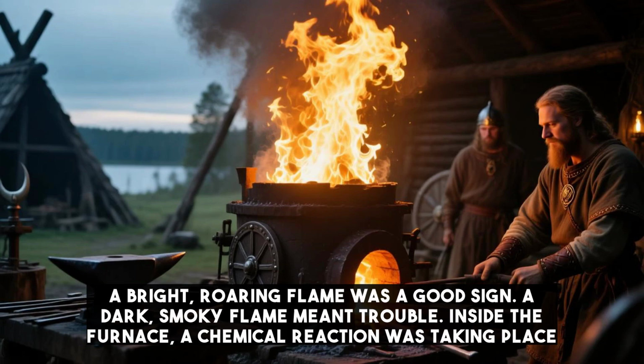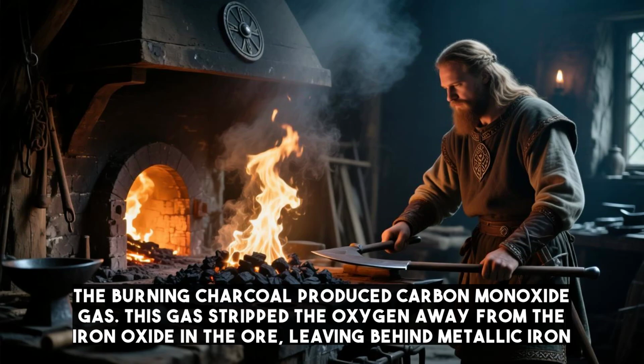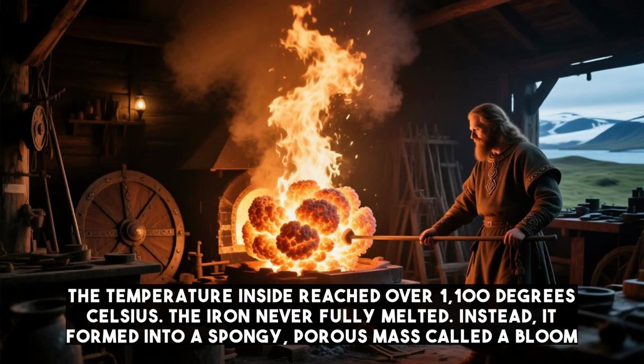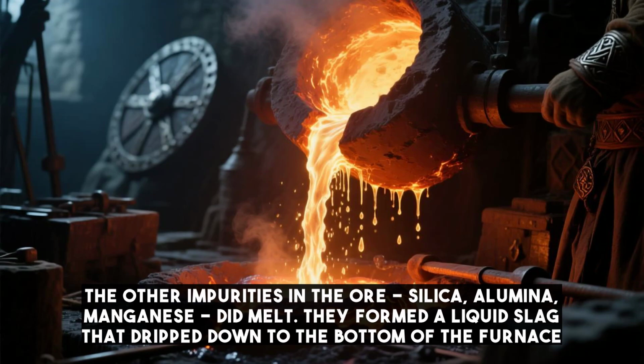Inside the furnace, a chemical reaction was taking place. The burning charcoal produced carbon monoxide gas. This gas stripped the oxygen away from the iron oxide in the ore, leaving behind metallic iron. The temperature inside reached over 1,100 degrees Celsius. The iron never fully melted. Instead, it formed into a spongy, porous mass called a bloom. The other impurities in the ore, silica, alumina, manganese, did melt. They formed a liquid slag that dripped down to the bottom of the furnace.